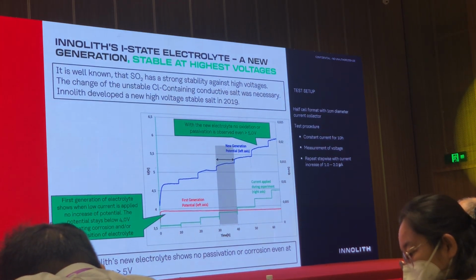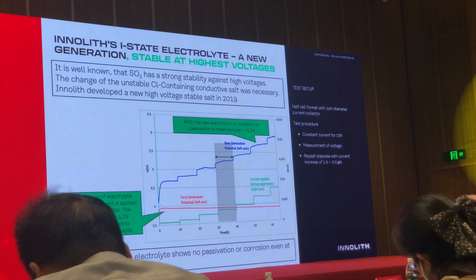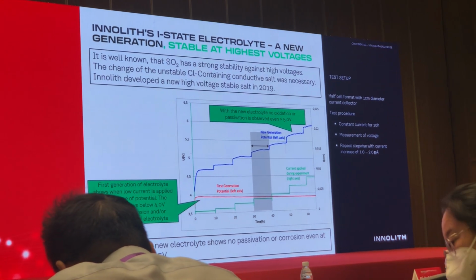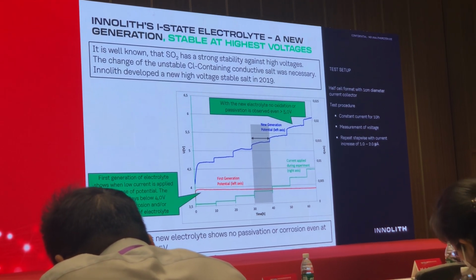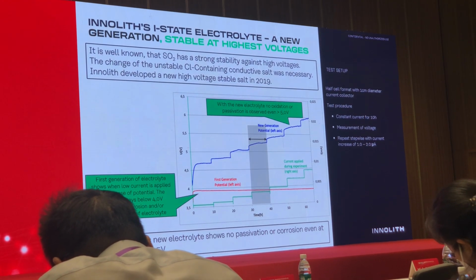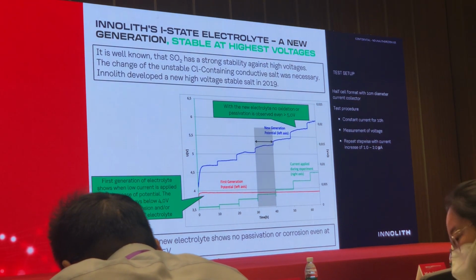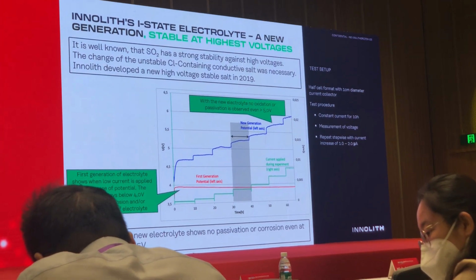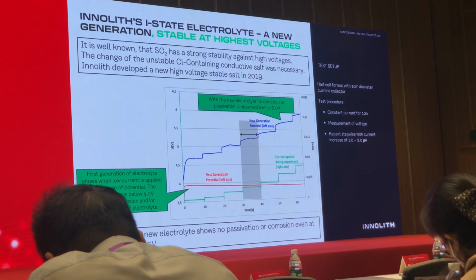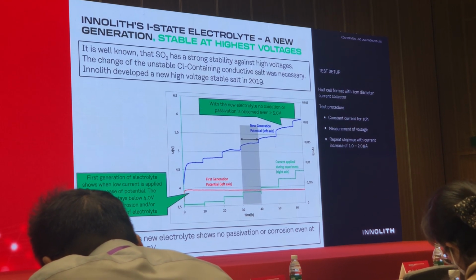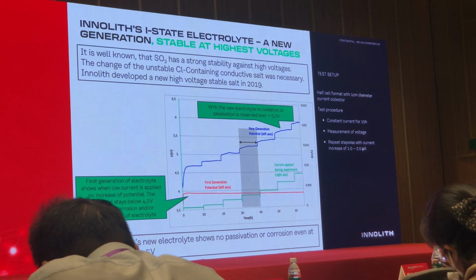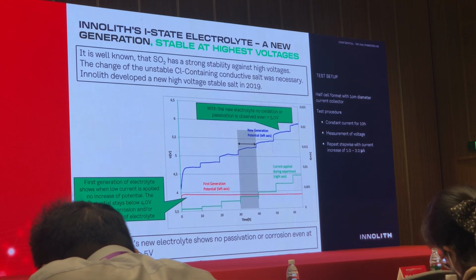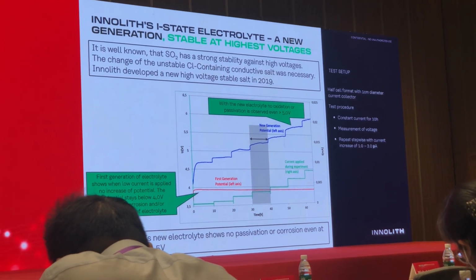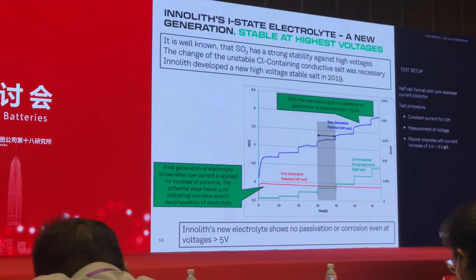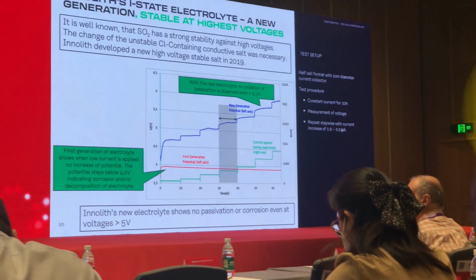What we have done in 2018 at Innolith is we did a large screening to solve exactly this issue of oxidation stability. And we tried to find a way to stabilize the unstable chloride bonding. More than 50 different salts were investigated, also a lot of different recipes on the electrolyte side.